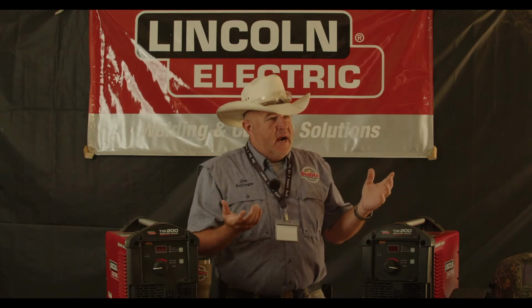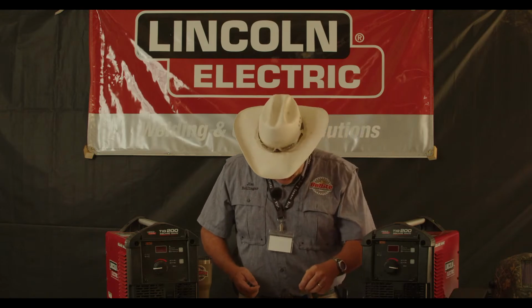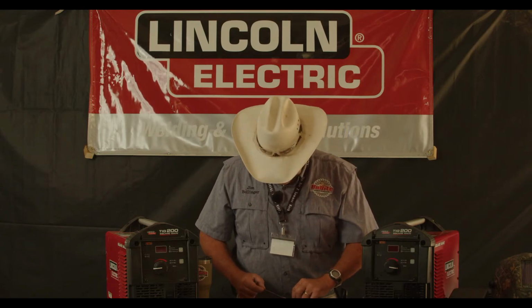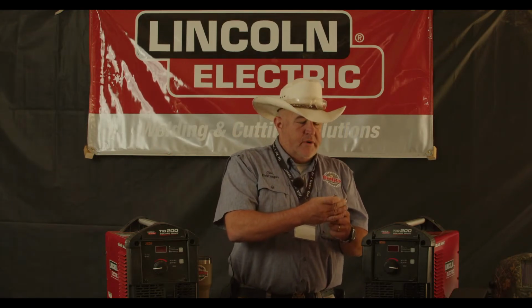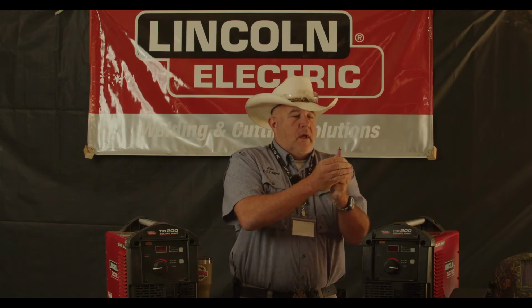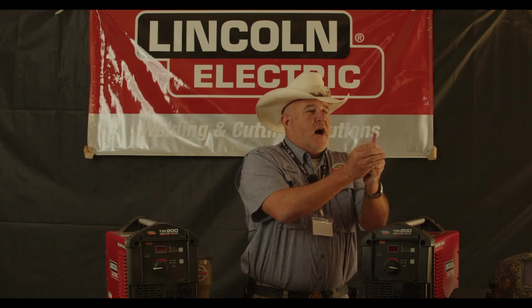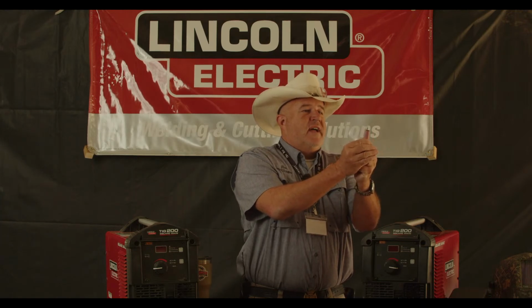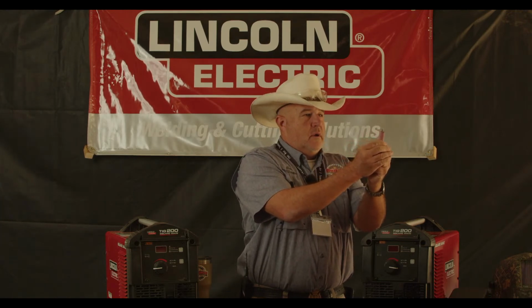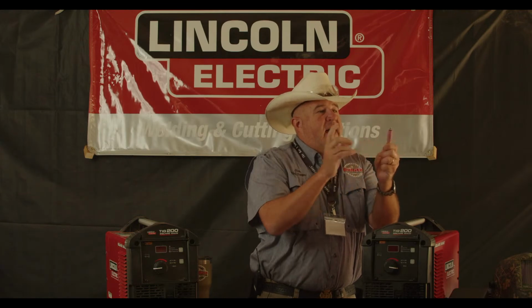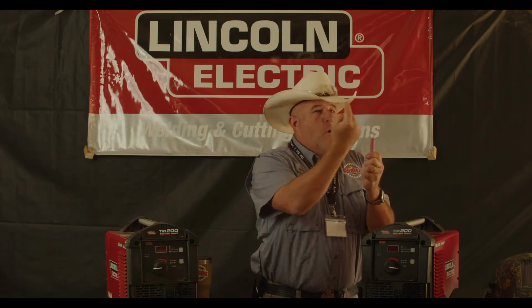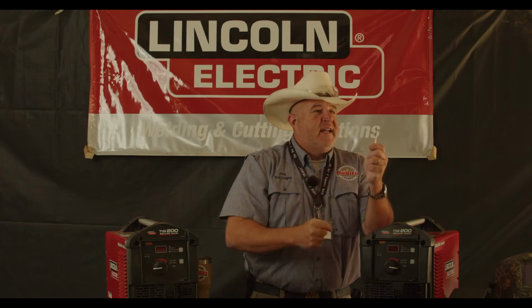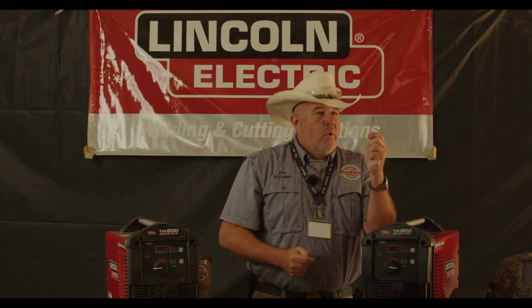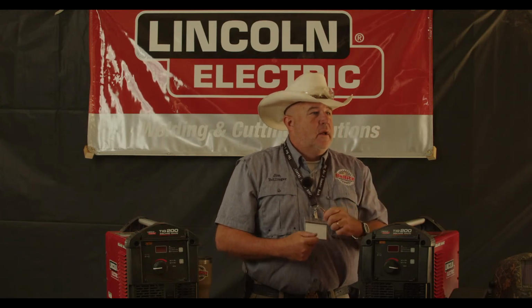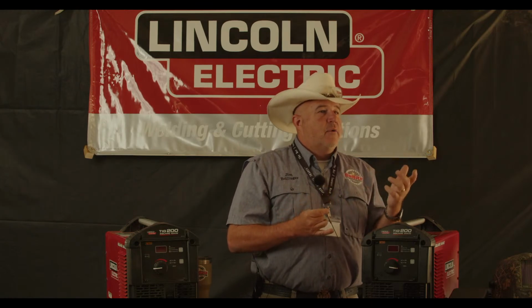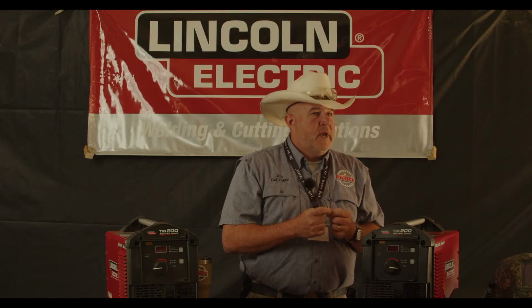Well, why do we even care? Well, there's a reason. If we were sticking a tungsten out and we were using a standard collet body, we could probably get away with sticking that tungsten out about that far. Any further than that, and that gas whipping around will whip oxygen in, and that oxygen will hit that tip. And when that's 5,000 degrees and oxygen hits it, the tip is ruined. You got to take it out and regrind the tip. And we'll talk about that in a few minutes.